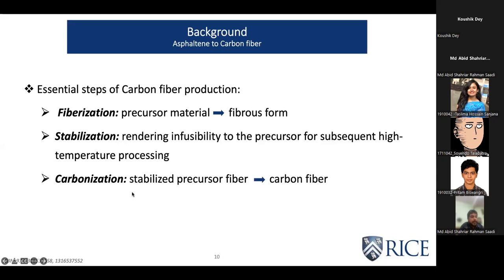We are cross-linking them and converting those thermoplastic fibers to thermosets. And this is necessary because the subsequent steps, for example, carbonization, which takes place at close to 1000 degrees Celsius, you have to give the fibers some kind of stability to sustain at that high temperature. So stabilization is the step where we provide the fibers that stability so that they can sustain the carbonization.